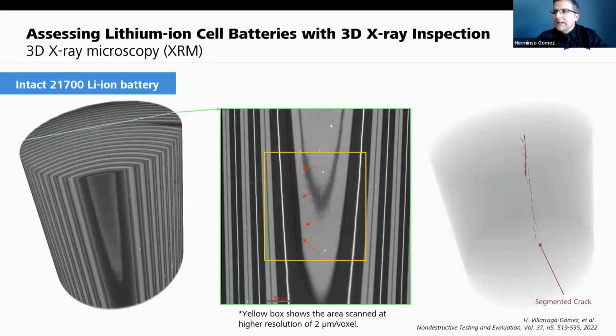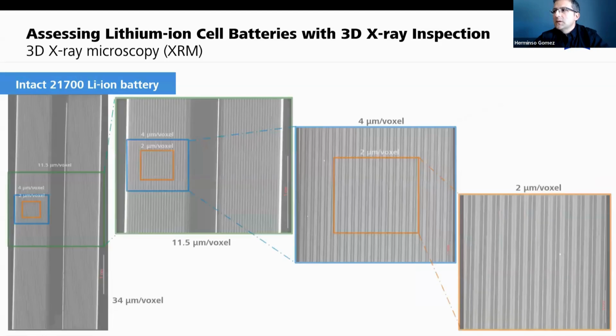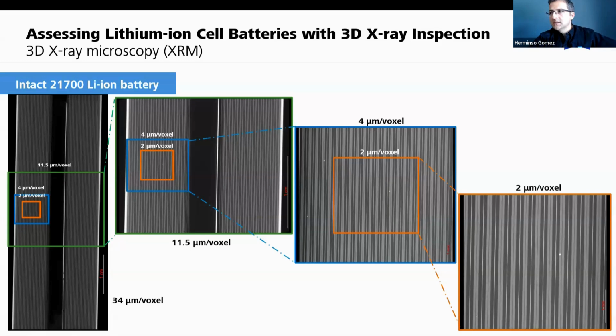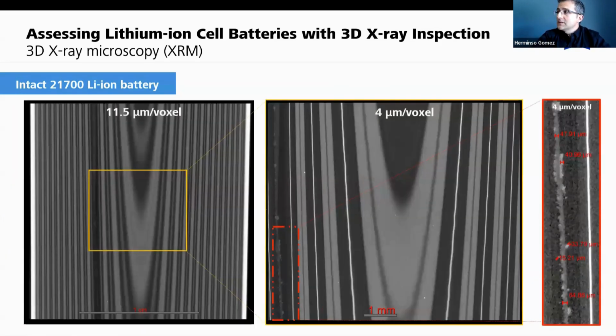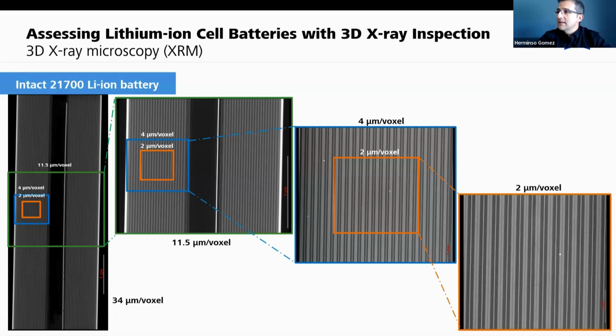And yes, for sure, you can look at particles, but there are other types of features that you would see, like cracks that are generated inside of the batteries after several cycles of charging and discharging. This can tell you how the battery is degrading over time. This is very typical, to do studies over several cycles of charging and discharging. The workflow, if I were to simplify a little bit, and let me go back to the previous slide, would show you that you can get a low resolution scan of the full battery and then zoom in with lenses into different sections of the battery to get the highest resolution, down to 2 micron voxel size or below if you want.